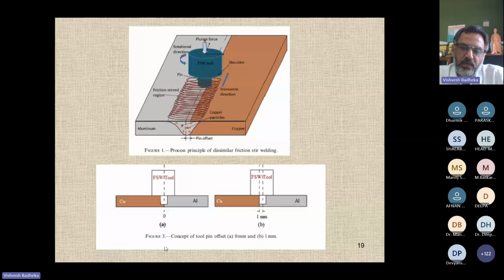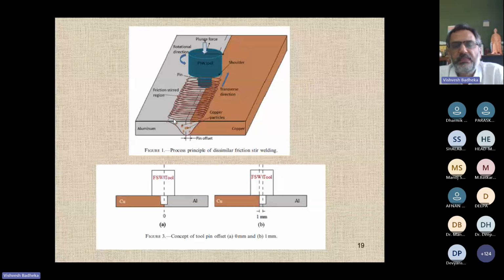Now you see with a more simple diagram, there is aluminum and copper. You can see there is a zero offset, right? Exactly, the centers are matching. But if you want to play with a 1 millimeter offset, you see that the joint line is here, and from the joint line, you are 1 millimeter away. And there you are plunging your tool. So this is called offset. Similarly, depending on the pin diameter, the maximum offset will be half of the pin diameter. And you can see that a lot of copper particles are mixing in the matrix. So the final microstructure is nothing but a matrix of aluminum wherein you can see a lot of copper particles mixed with the matrix material.